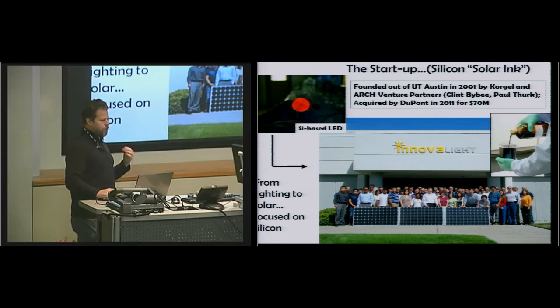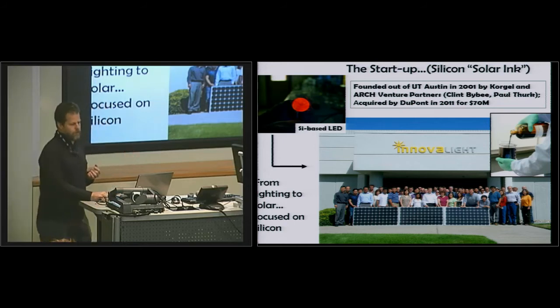One of the initial ideas for our silicon ink was to actually paint a solar cell with silicon. The problem with that is you're taking an indirect bandgap semiconductor material and painting it on, and you have to use a lot of material to absorb the light. So it didn't really make sense to try to do that. What the company ended up doing was taking the silicon ink, which is highly doped, and making selective emitter devices on single crystal silicon.